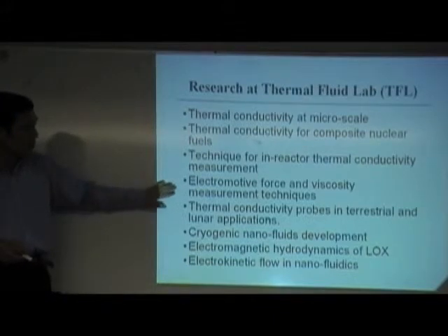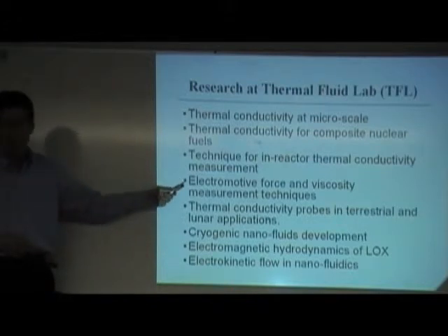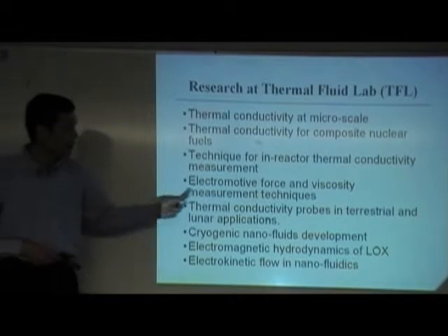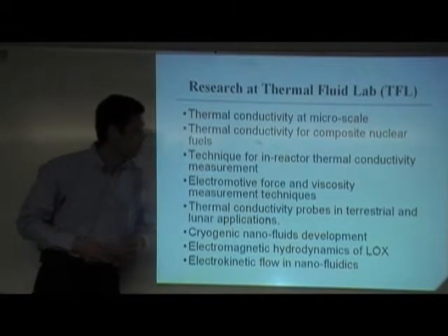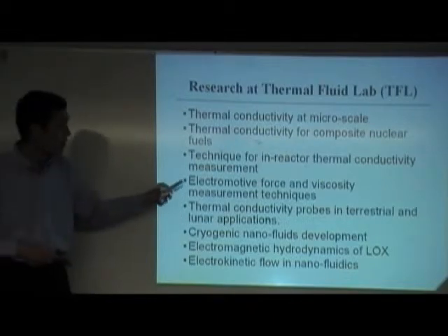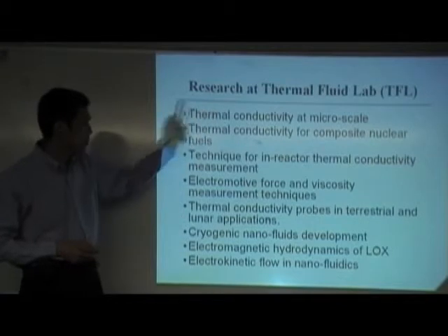We also have some other thermophysical property work. One is the electromotive force, which is basically the thermocouple. How do you measure the thermocouple? It's the voltage generated by a temperature difference. That is something you can use to calculate phase diagrams and the Gibbs function of the material itself. And also viscosity. It's a special measurement for high temperature viscosity, so it's a little different. I'm going to talk about this one, and Zilong is going to talk about this one.